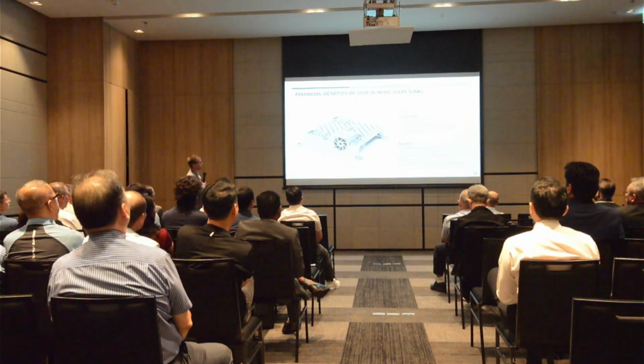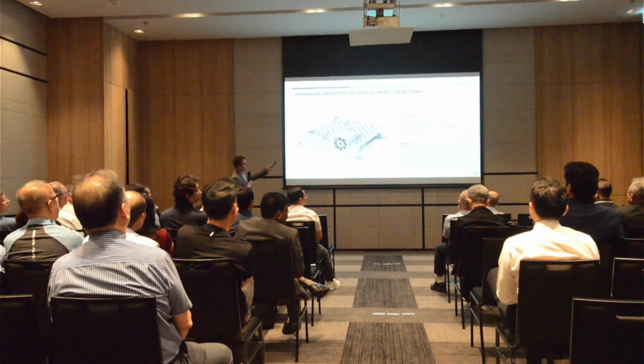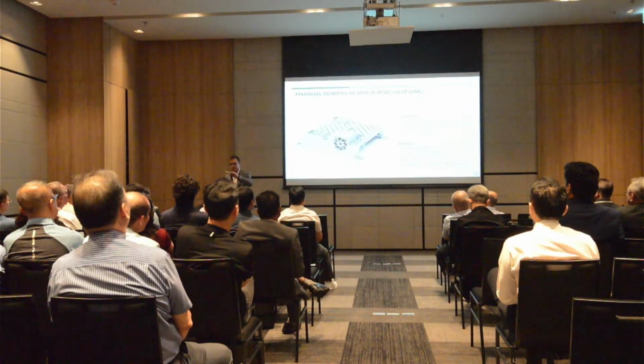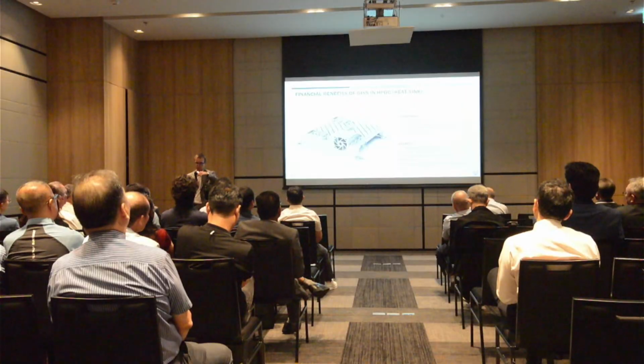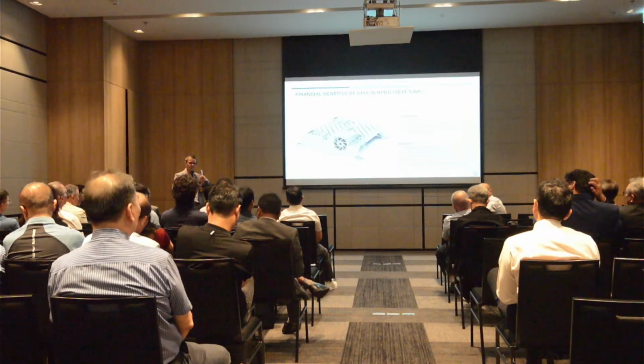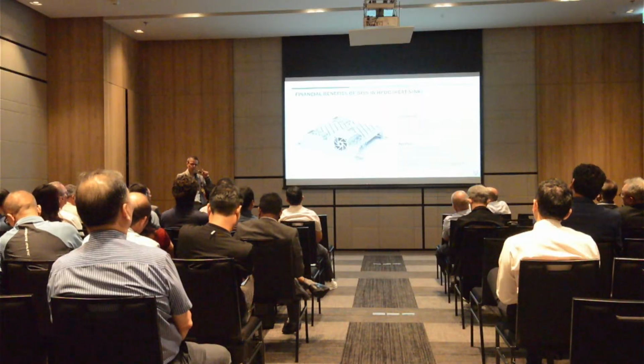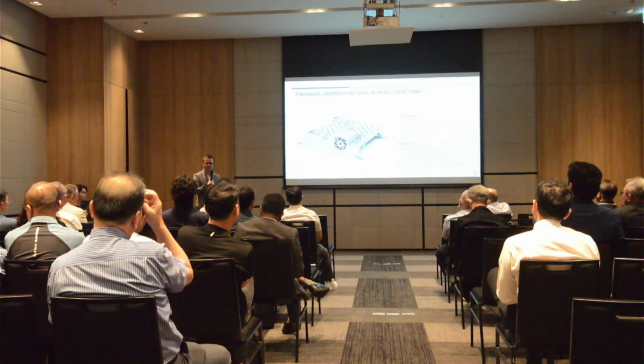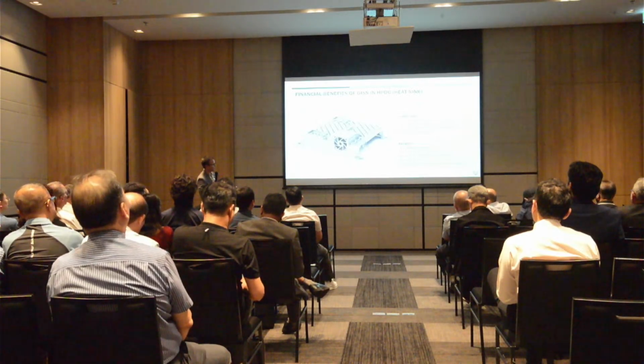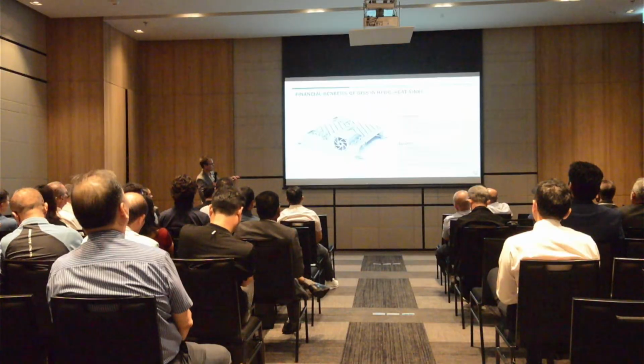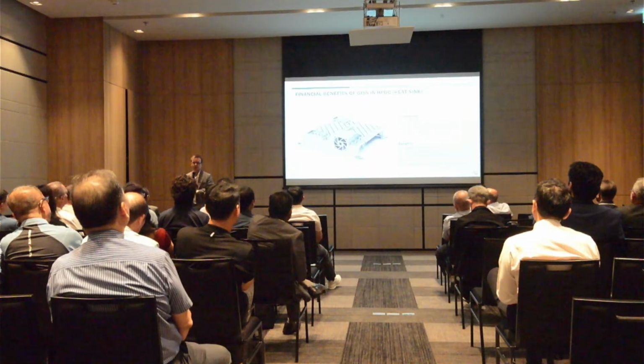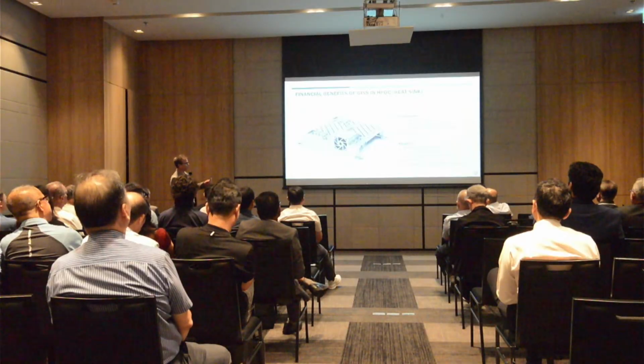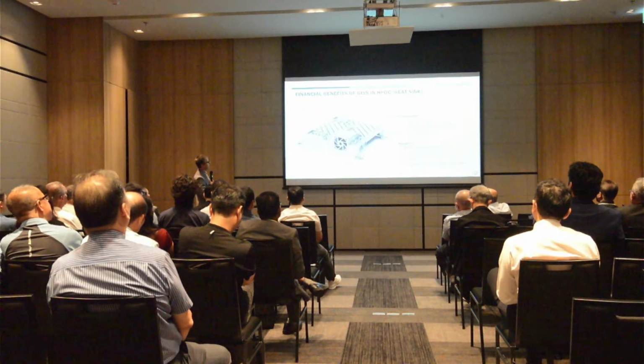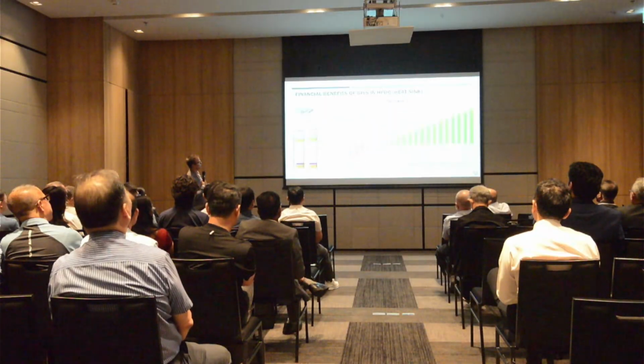And also here we were able to increase the die life 50%. In these typical components, you have a lot of issues with ejector pins. You have the holes for the self-drilling screws. You have the flatness. You have the areas where the ICs are contacting, so you are not allowed to have any pickles on the surface. So very sensitive areas to transfer the heat from the electric part to the housing. And also here we were able to slightly reduce the cycle time. We had less stoppages to the die. We were achieving the same quality, so there was no big impact on quality improvement. And also here we had the lower furnace temperature and the thermal balancement, which of course also factored into the calculation.